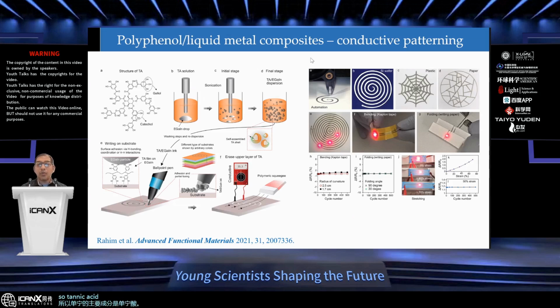So the main component of tannin is tannic acid. One important connection is that there is another big field, the bio-inspired field, that possibly you are pretty well aware of, mussel-inspired chemistry, which essentially deals with catechol chemistry. And this tannic acid has a lot of catechol groups that can attach to any surface. So the idea was, can we modify the liquid metal particles with this sort of surface active agent which contains catechol, and use the adhesive properties of the polyphenolic structure to make them write on any surface? And this is exactly what we did.